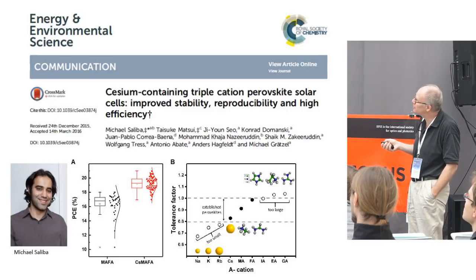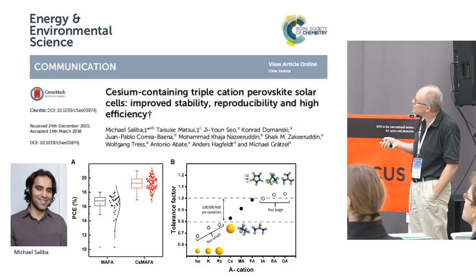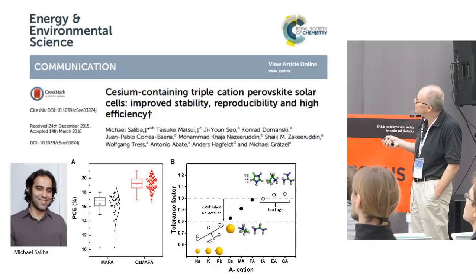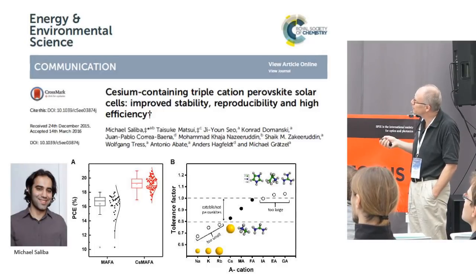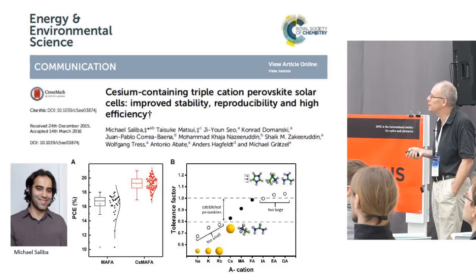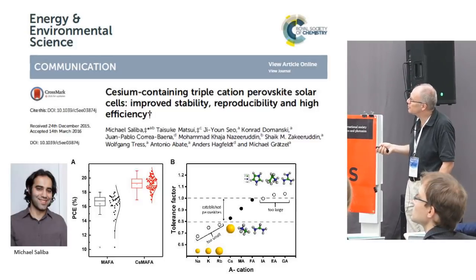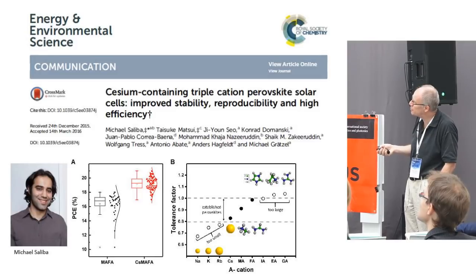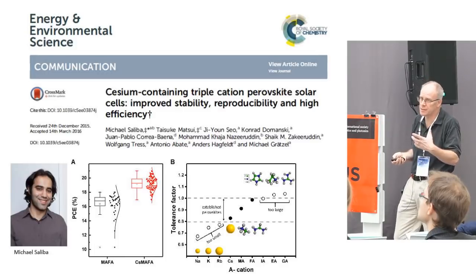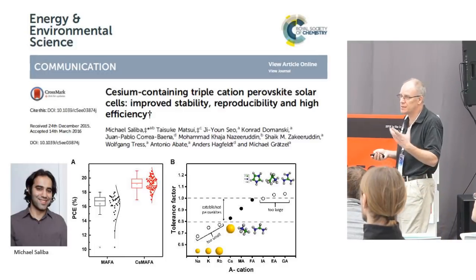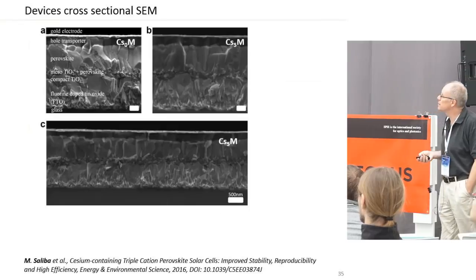But cesium did well, and so this cesium was added to become the triple cation, and that improved things quite a lot. So we had higher efficiencies and also better statistics. This is the reproducibility, let's say, average values. So you see also triple cation compared to double cation, much better with the triple. Stability became better and so on. So that's still something we try to understand, why this mixed is such a good strategy.